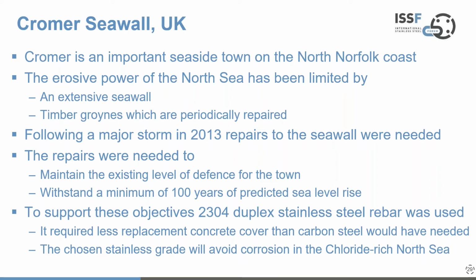similarities between this and the Bayonne Breakwater, where less replacement concrete was required to cover them than carbon steel would have needed, because carbon steel will obviously corrode in this environment and duplex stainless will not, and the additional strength brings additional benefits. And we know that we're going to let this revised or rebuilt seawall survive for 100 years, even with extreme events from the chloride-rich North Sea. So this is just a sort of mirror, really, of the work done in France. Same sorts of requirements, same choice of materials, combination of stainless steel rebar and concrete.